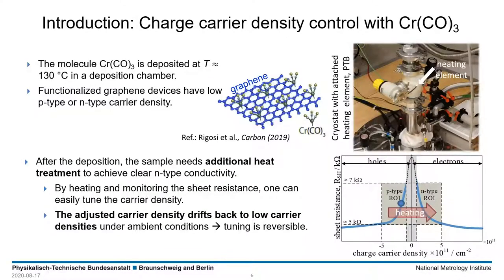At NIST, Albert Rigosi and I were working on a doping technique where the graphene is functionalized with chromium tricarbonyl, which allows for tuning the carrier density to the desired value afterward. The initial low P-type or N-type doping level is shifted deeper into the N-type region by heating the sample. At PTB, we attach the heating element to our cryostat to realize the procedure. Since the tuning procedure works very reliably and the process is reversible, it provides a high degree of flexibility.